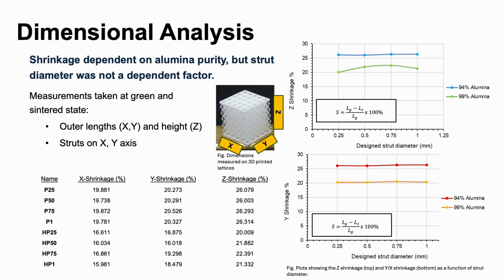This result was also seen in these plots here, where we correlated the Z and Y shrinkage to the design strut diameter. There was no correlation seen as a function of strut diameter. However, the shrinkage was larger for 94% alumina by about 6%.